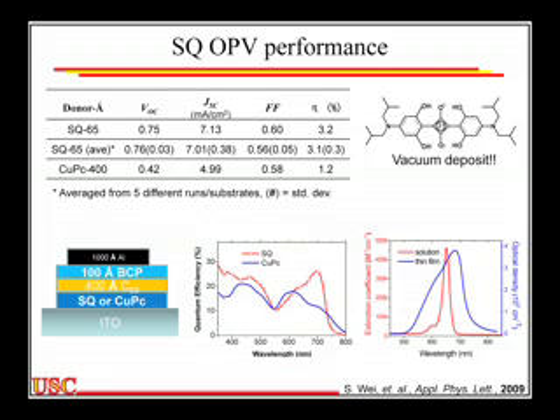But the key is these were bulk heterojunctions made by putting down a homogeneous film and annealing them. So they don't know anything about the spacing in these. And so we wanted to go back and make lamellar devices where we could carefully control the thickness and potentially learn something about these as a class of donors. What's the diffusion length look like? How good are they at transporting holes, and so on.